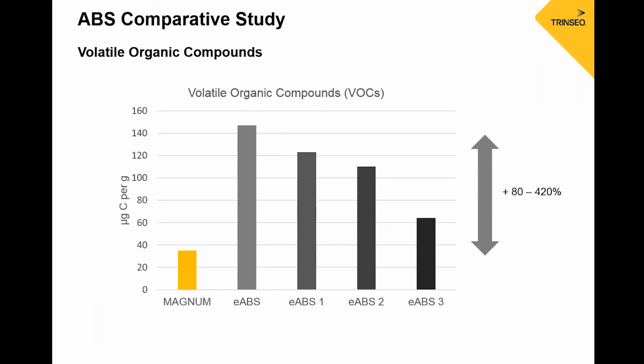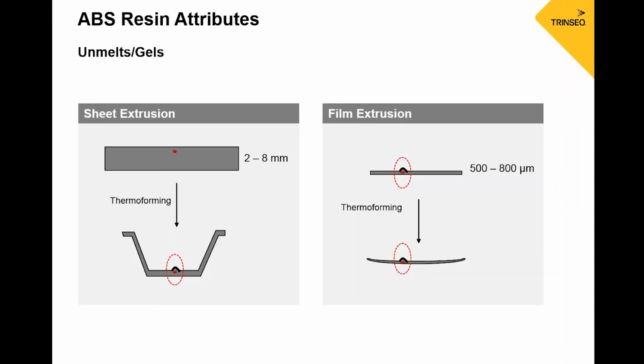And where that comes into play is with the VOCs, the volatile organic compounds, which are becoming very important in many applications, especially it's been very important in automotive, becoming more and more important in indoor applications, but it's also important for the processors, the processing and the smells that you smell during processing are resulting from the VOC levels. And so we measured this in these products using headspace gas chromatography, and the units are in micrograms of carbon per gram of ABS. So we can see a large percentage change in those VOC levels with this Magnum ABS versus the emulsion ABS, anywhere from 80 to 420% increase in those levels.